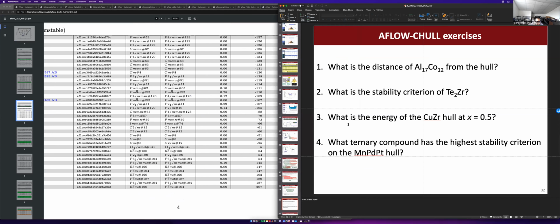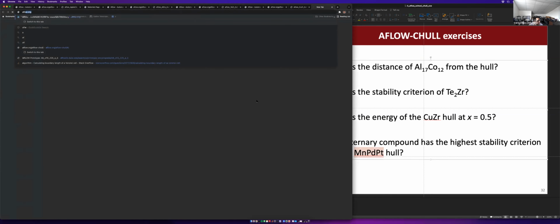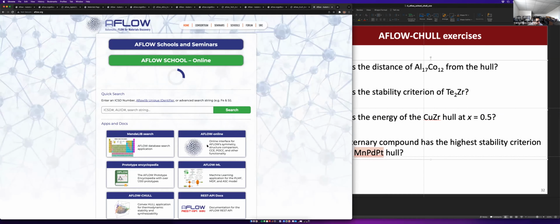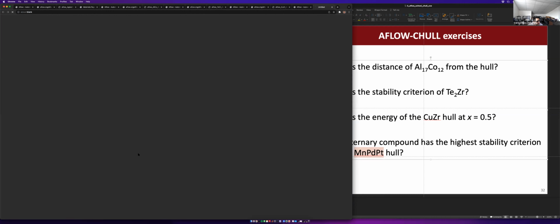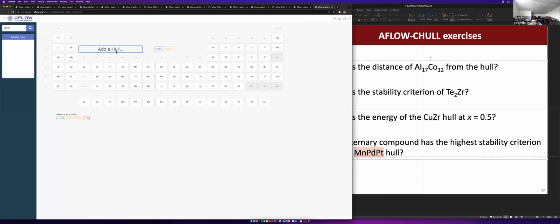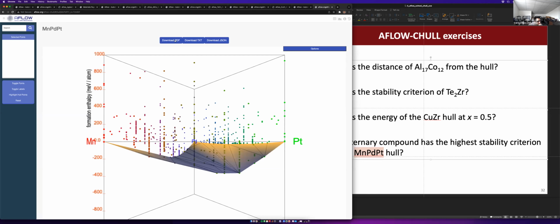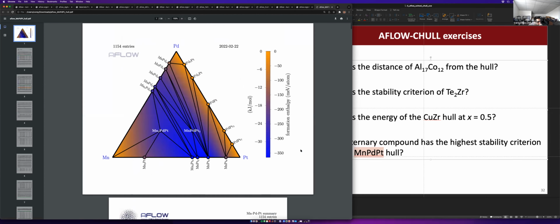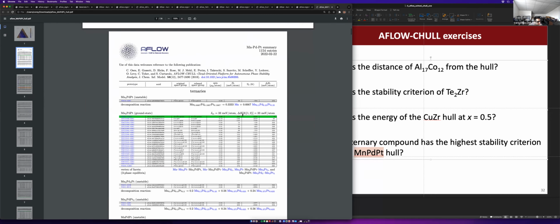Anyway, the last question is: which ternary compound has the highest stability criterion on this hull? So we're going to open that up, go to convex hull, hit submit, and download the PDF. We open that up, and you see that there are not many ternaries. Here this stability criterion is 33 meV per atom.